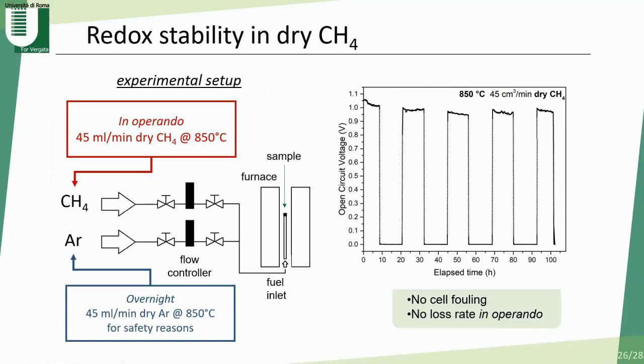Firstly, we were interested to check the redox stability in these conditions. So we switched between methane during the day and argon during the night for 1 week. And we could observe, firstly, that the OCV in methane is quite good. It is about 1 volt, which is good. It means that the anode is properly working, and we could not observe any decrease and no cell fouling after one week.